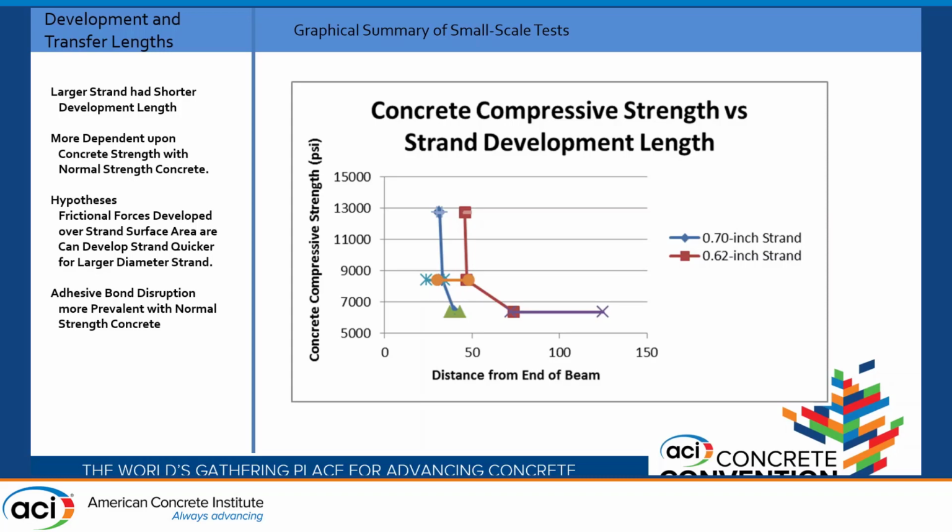And considerably shorter than the ACI or the AASHTO requirements would lead you to believe. Notice too that the lower the concrete strength, the curve here requires longer development length. So the tests are showing that concrete strength does improve or shorten the development